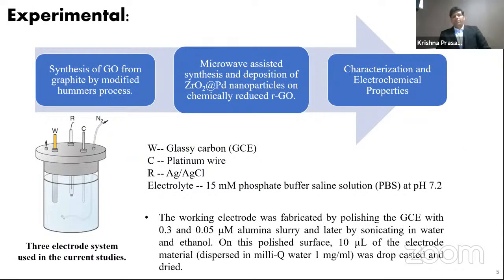So coming to the experimental part, what we have done is that we have synthesized graphite oxide from graphite using the modified Hummers procedure. And this graphite oxide was used in a microwave assisted reduction procedure using hydrazine to synthesize the zirconia on palladium nanoparticles. This particular composite has been characterized, and its electrochemical properties towards the detection of methyl parathion have been studied.